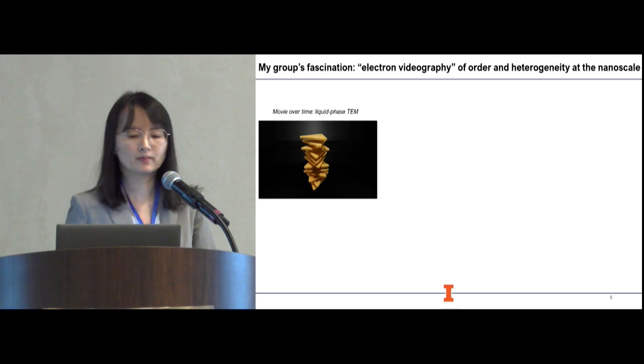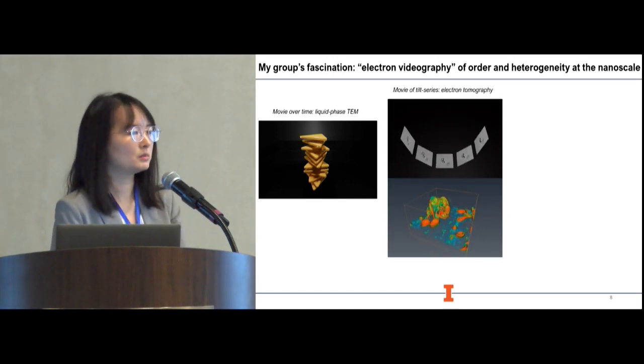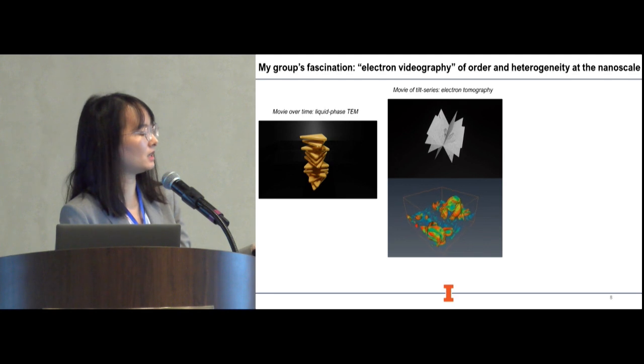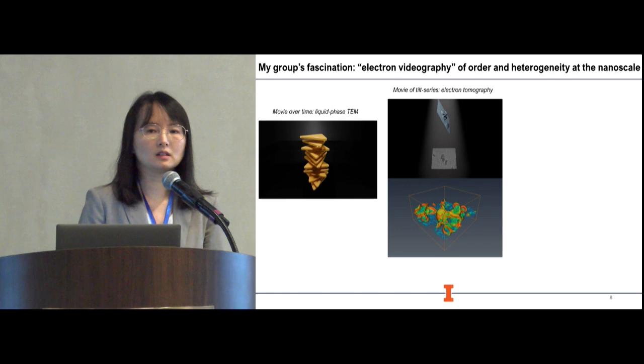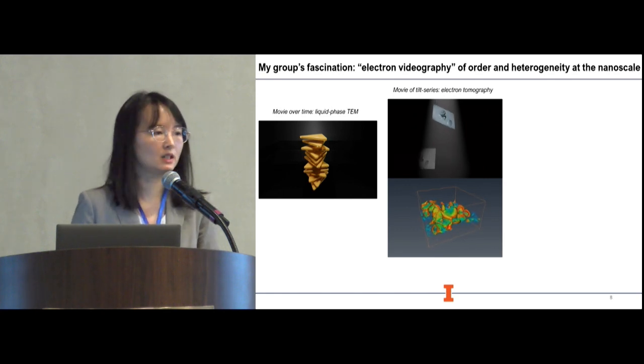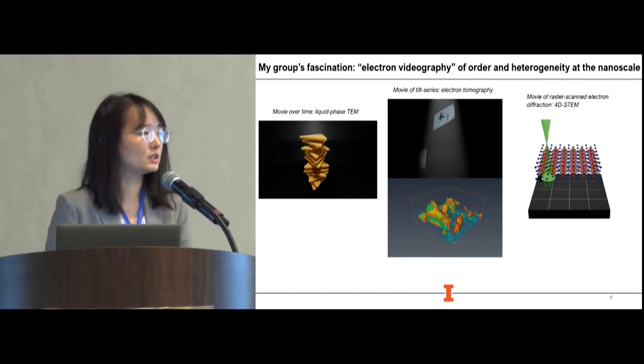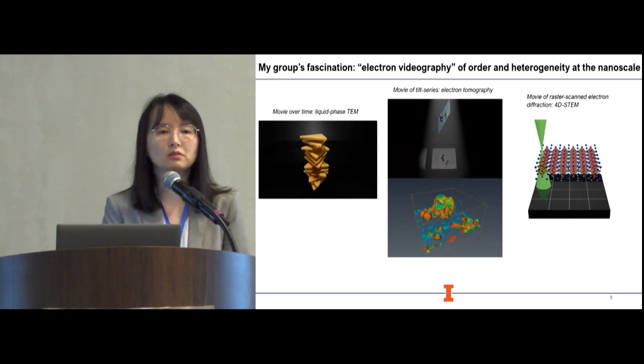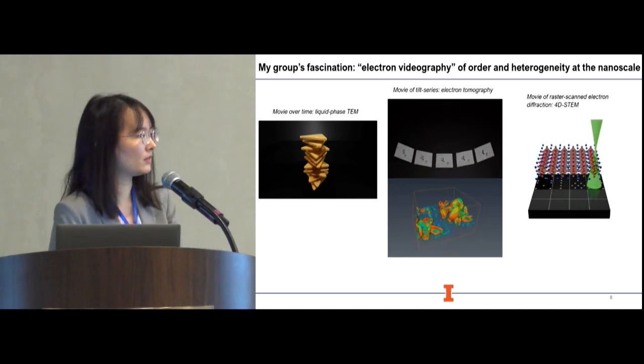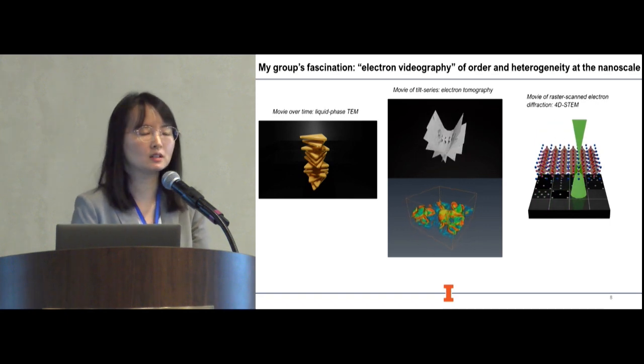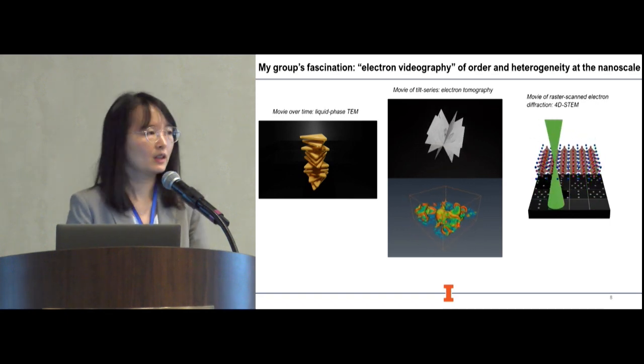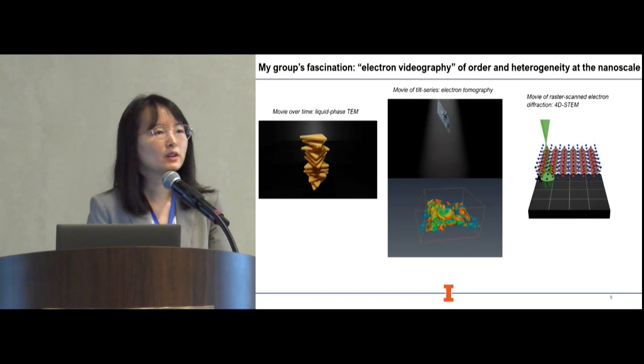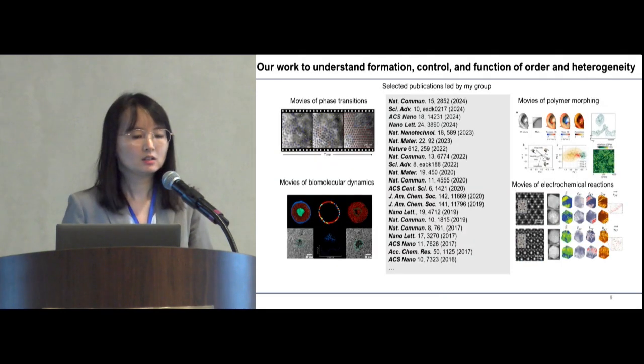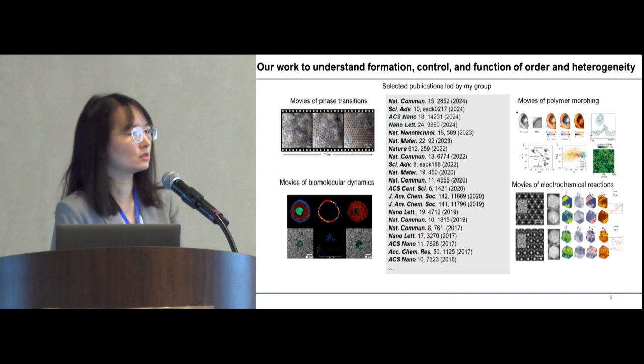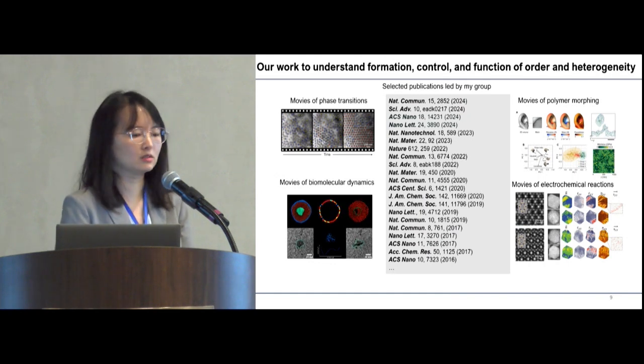The second is electron tomography, where you can resolve the complicated 3-dimensional structure of a sample at the otherwise inaccessible sub-nanometer voxel resolution. And the last one is 4D scan, which allows you to image the defects, strain, crystalline phase, and crystal phase orientation at the nanometer resolution. All those 3 electron videography methods are fairly recent. That's why we're able to utilize those methods to study a diversity of systems.